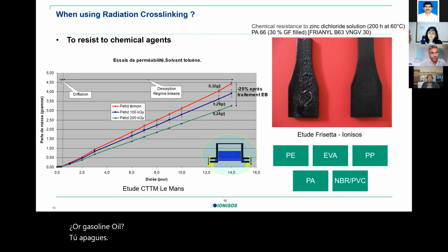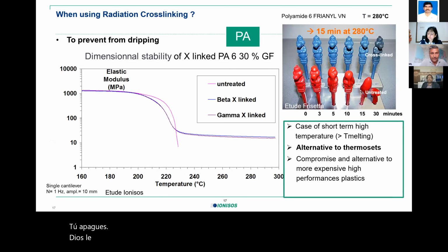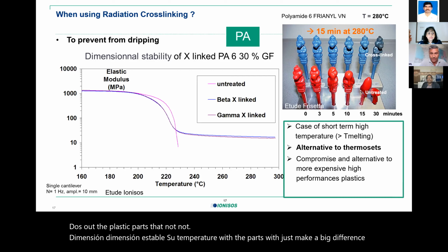The other important property that we are looking into is the thermal resistance. In this case, we have an example of a polyamide that we have irradiated by E-beam and by gamma to the same dose, and you can see there how the plastic parts that were not cross-linked are not dimensionally stable to temperature, while when we irradiate the parts, we make a big difference, and the part is quite stable at high temperatures.